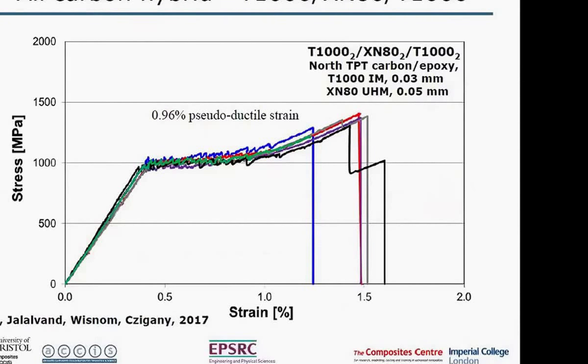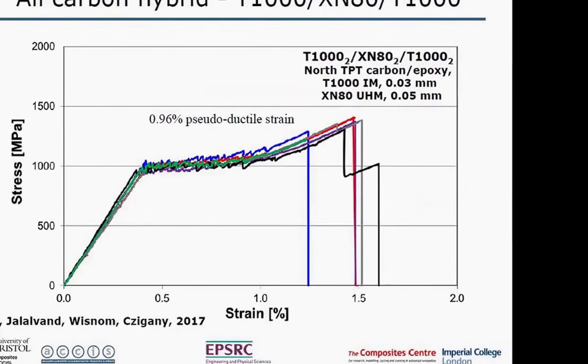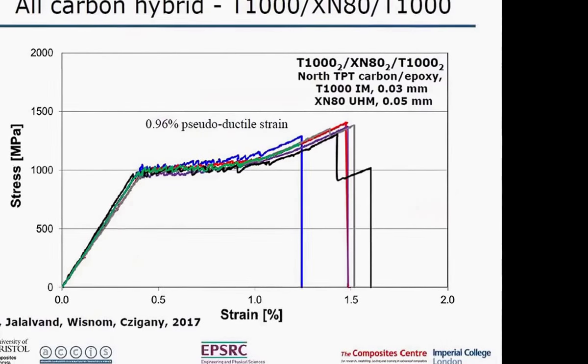But we can do the same thing with different grades of carbon. This plot here shows an all-carbon configuration where we've got T1000 and XN80. So XN80 is a very high modulus fiber, and we've got that sandwiched between T1000, which is an intermediate modulus, high strength fiber, and you see we get the same sort of pseudo-ductile response with initial elastic response, this plateau, where we get fragmentation, and in this case about 1% pseudo-ductile strain.